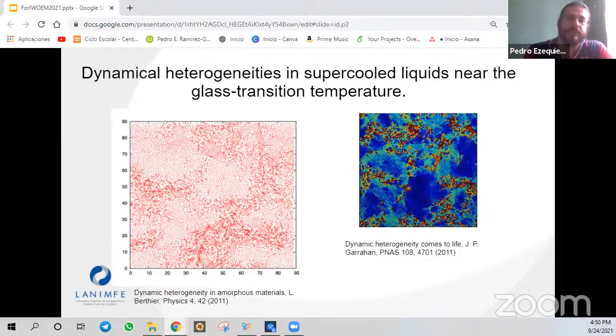Now, dynamical heterogeneity is another essential feature of the disordered materials, which emerged from experimental studies of viscous molecular liquids near the glass transition. In these systems, local relaxation is measured by mechanical or dielectric probes, showing a wide range of non-exponential relaxation times. Indeed, using computer simulations to study supercooled liquids, we can observe that two important characteristics of particle motion inside the fluid are, first, that they are highly intermittent, and the trajectories differ widely from one particle to another in the same system at the same time. So this is very important for many glass formers, even for glass formers formed by living cells or something like that.